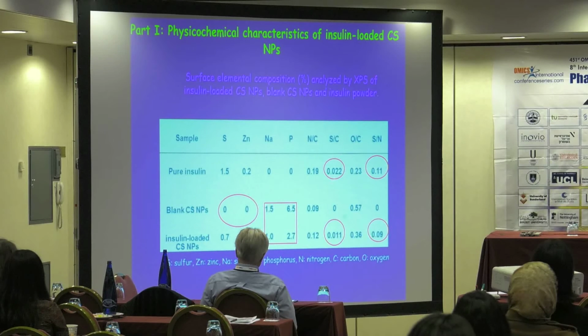This means that we have similarities between the surface of pure insulin and insulin-loaded chitosan particles. However, the ratios were higher in the case of pure insulin, and this tells us that we have a proportion of insulin adsorbed on the surface of the chitosan nanoparticles.